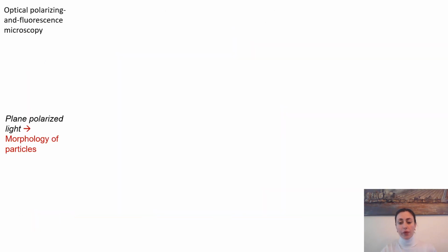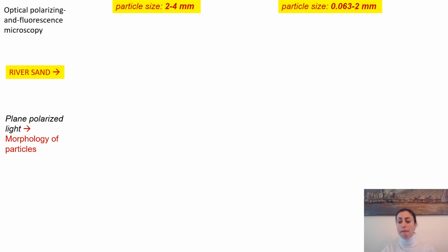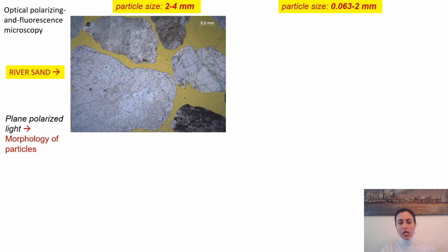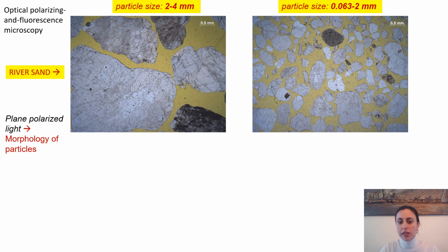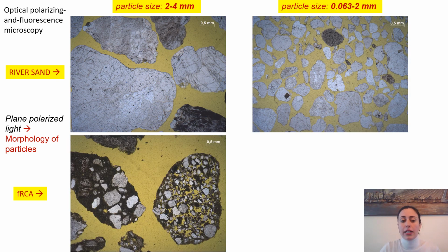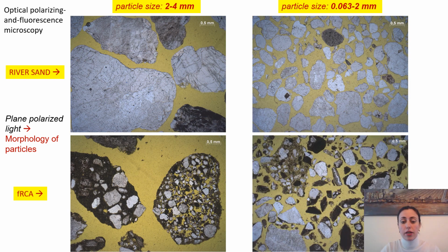Further, I would like to give you an illustration of how this material looks on a micro level, for two different groups of particles, one is 2 to 4 millimeter and one is below 2 millimeter. What we can see here is that the river sand has perfectly shaped particles, which are mainly white. In recycled concrete aggregate particles, we can see something which is actually cement paste.